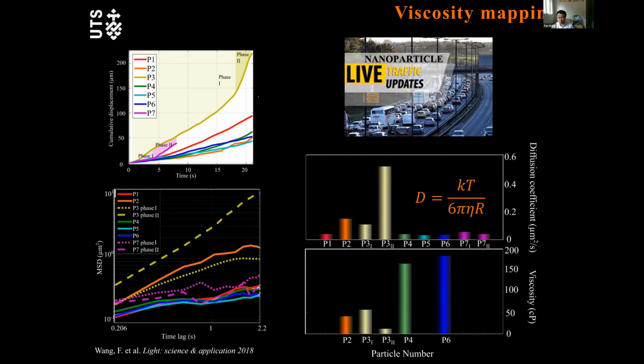So this is going to be pretty useful because you can see that these two particles, from the previous image, are actually inside the nucleus of the cell, and those three are outside the nucleus, and the P3 for this phase actually goes through the microtubule. So for different positions, you can map out the viscosity.